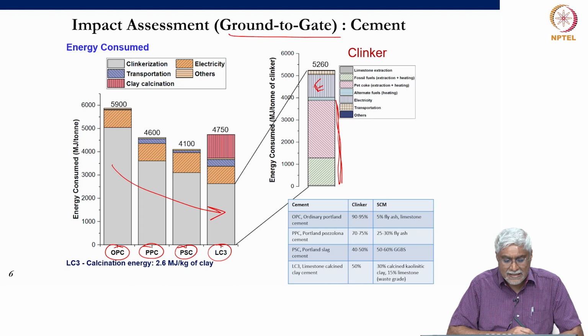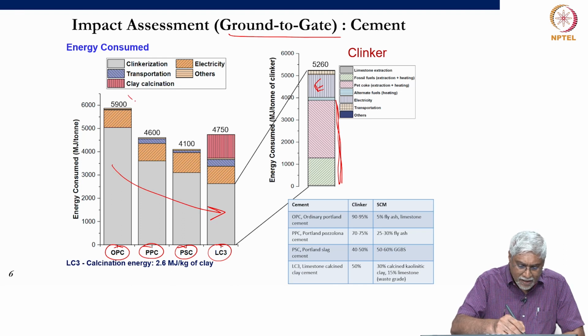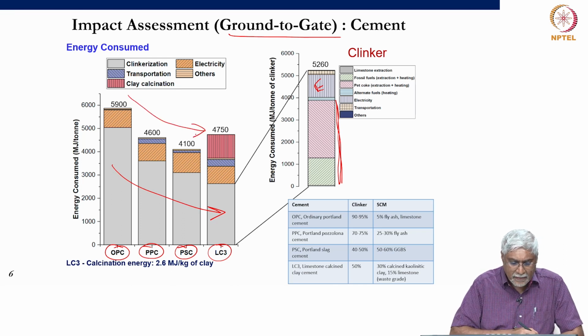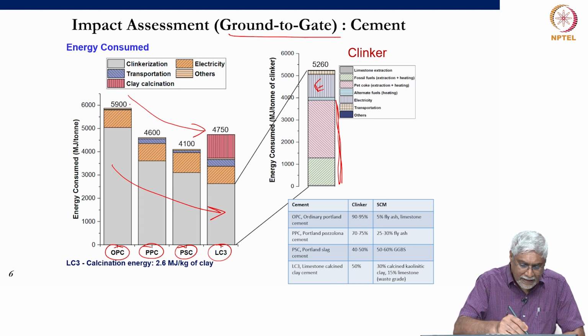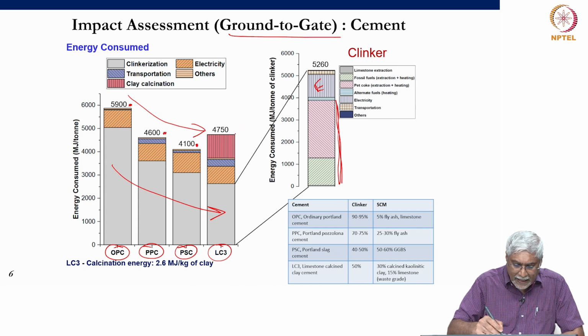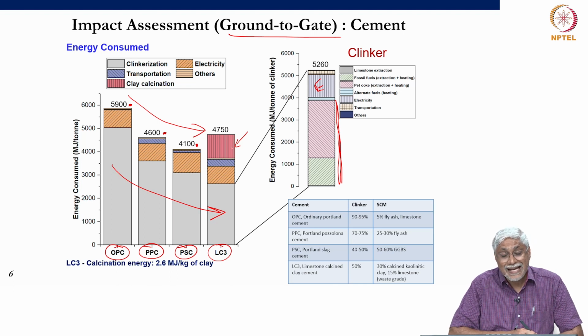Consequently, as we decrease the clinker content, we find that the overall energy requirement also decreases. Similar to what we saw before, from 5900 in the case of OPC, for PPC the value comes down to 4600, PSC 4100. For the case of LC3, it will be more than the PPC and PSC because we also need energy for the calcination of the clay. It is less than that of clinker because the temperature required for calcination of the clay is about 700 to 900 degrees Celsius instead of 1500 that you would have in a clinkering kiln.